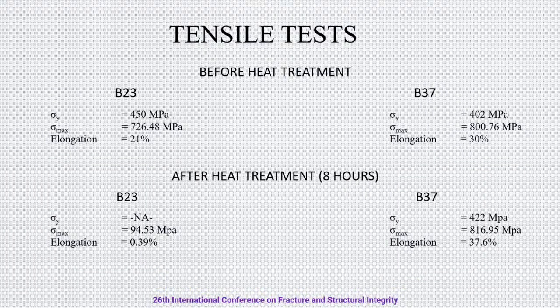After that, we did the tensile test. Before the heat treatment, both alloys B23 and B37 show similar mechanical behaviors. After heat treatment of 8 hours, B37 did not change its mechanical behavior, while B23 shows brittle behavior with almost no elastic behavior, and it was very, very brittle.